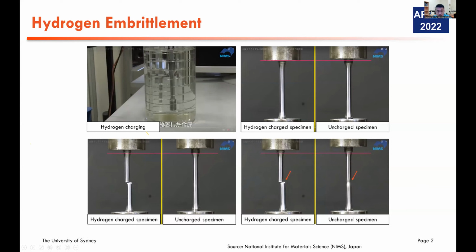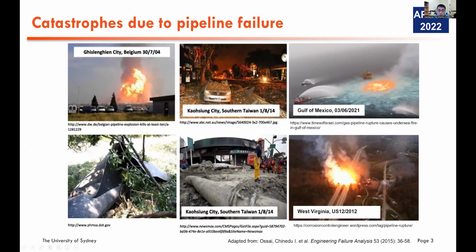Hydrogen embrittlement is a classic research and engineering topic that describes the mechanical degradation of materials exposed to a hydrogen environment. As you can see from the typical uniaxial tensile tests here, the left sample, which underwent hydrogen charging, shows much reduced ductility and a significant reduction in fracture toughness, showing brittle fracture instead of the normal ductile fracture behavior. Because of hydrogen embrittlement, the mechanical properties of materials become very unpredictable, which is a big problem for engineering, especially for pipeline networks, and especially considering the future endeavor of transporting hydrogen in those pipeline networks. We don't want these catastrophes to happen.